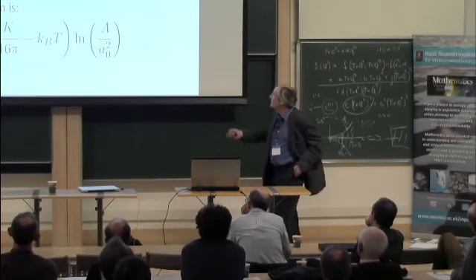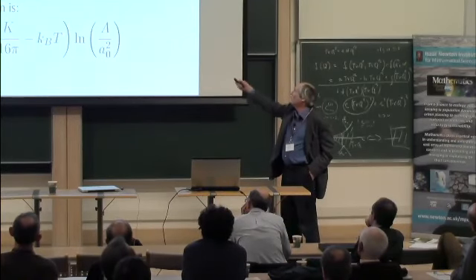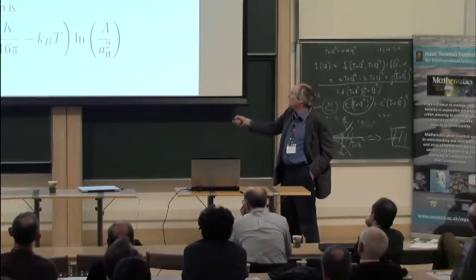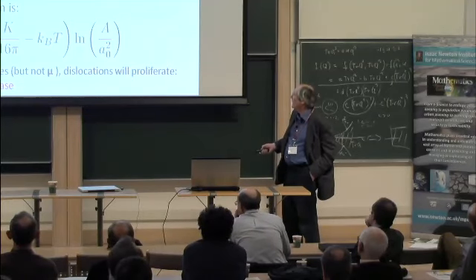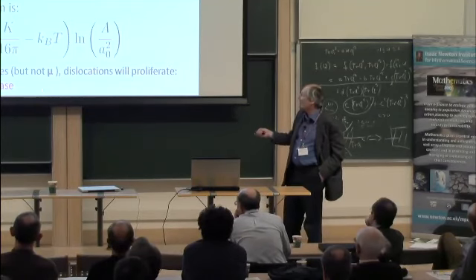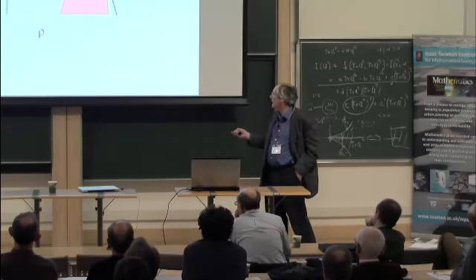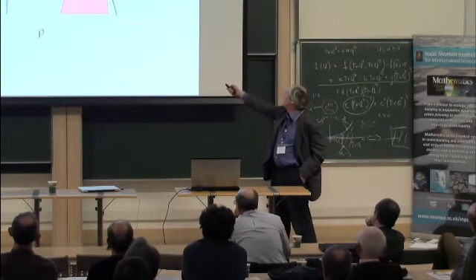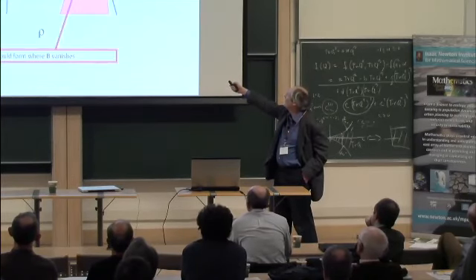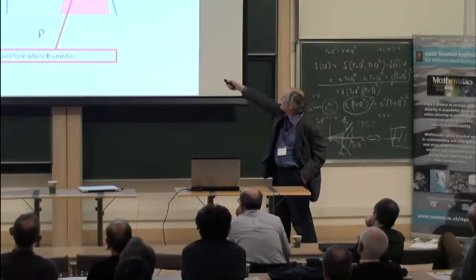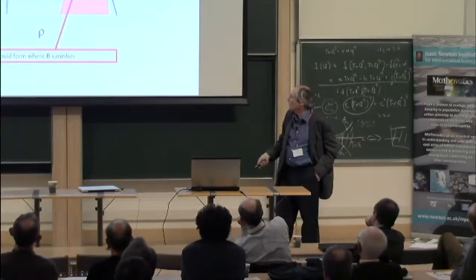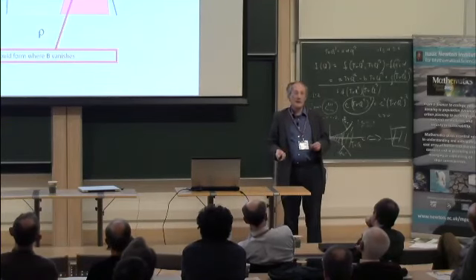Now curiously, if you have a situation where the bulk modulus vanishes, then this thing also would go to 0, and so that's what you expect: in the hexatic, these dislocations will proliferate, and in particular in this region where the bulk modulus is small. So it doesn't have to be just a point, but the whole region where it's small, you should see a hexatic phase.